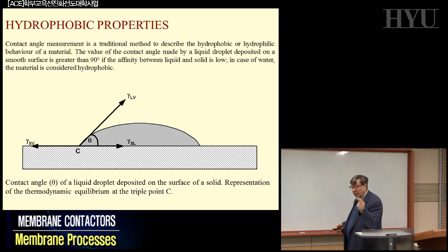If you have liquid, selectivity is going down, because with the liquid, solvent and solutes will penetrate. So basically you have a solution and you just don't have any fresh water on the other side. What you have to do for measuring the hydrophobic properties is to measure a contact angle, this angle here, that is of the order of higher than 95.